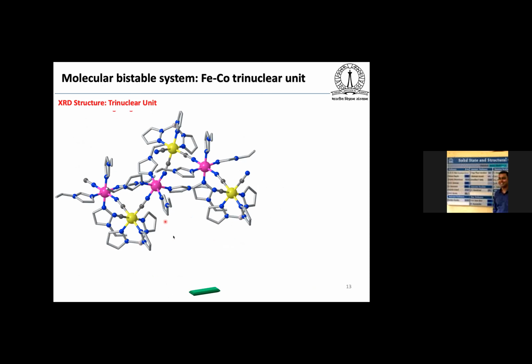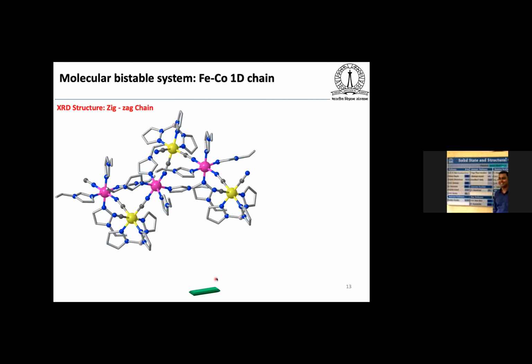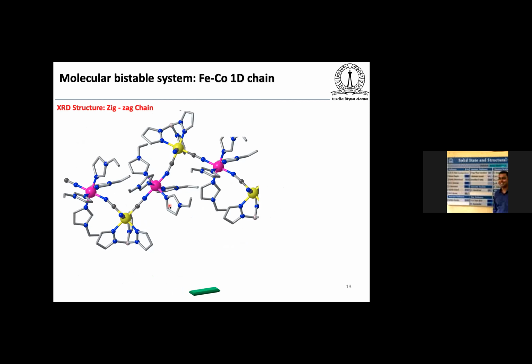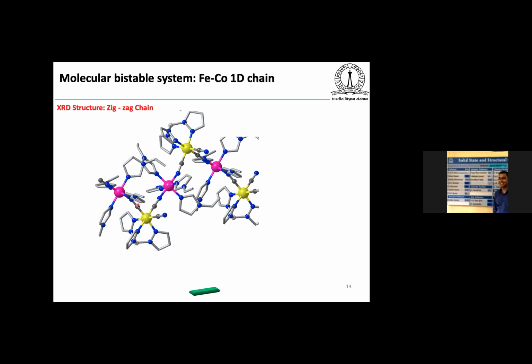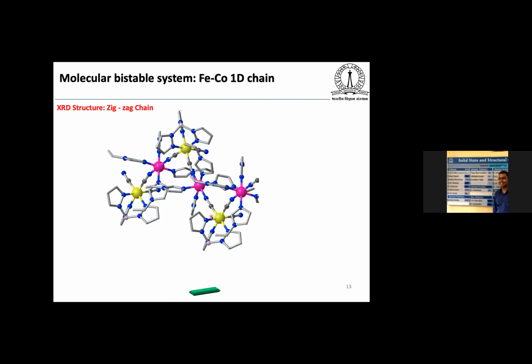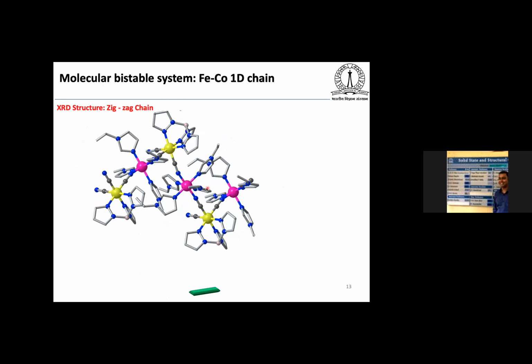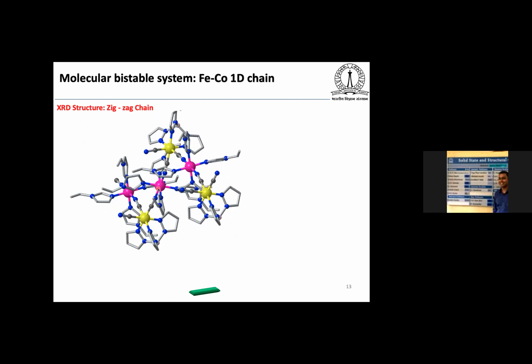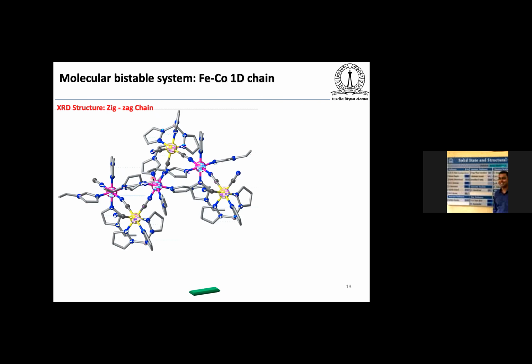And in case of the plate green crystals, we got a very interesting zigzag type of chain, where iron TP-CN3 is connected with two cobalt 2 units, where the cobalt is surrounded by 4 imidazole, vinyl imidazole systems. And here is the asymmetric unit. Here you can see we have one BF4 anion, we have one water molecule that is also connected with the strong hydrogen bonding on the cyanide side, and also we have one acetonitrile molecule in the systems.